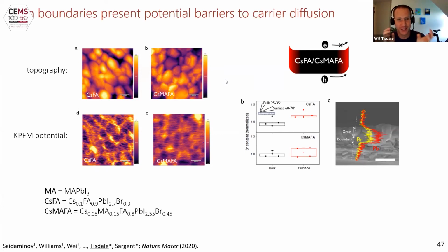We make the observation that in the single crystals there's no dependence on composition. In the polycrystalline samples there is a dependence on composition, and that leads us to hypothesize that the grain boundaries are to blame. Got it.